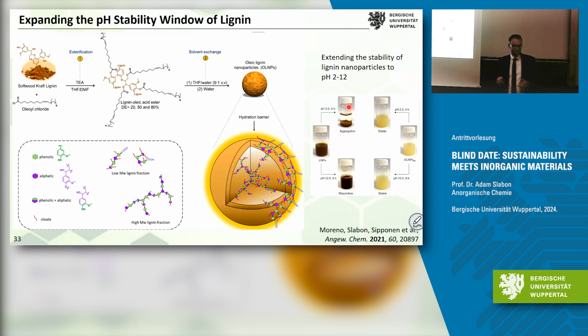And at pH 2 it agglomerates, it's a chunk. But if you make this reaction, you can expand the stability window for high pH, and you can also make the hydrothermal growth of materials.